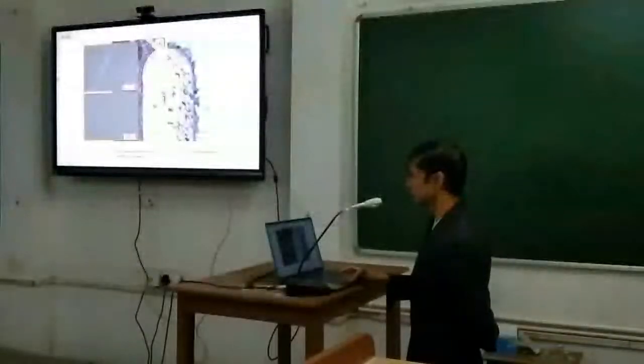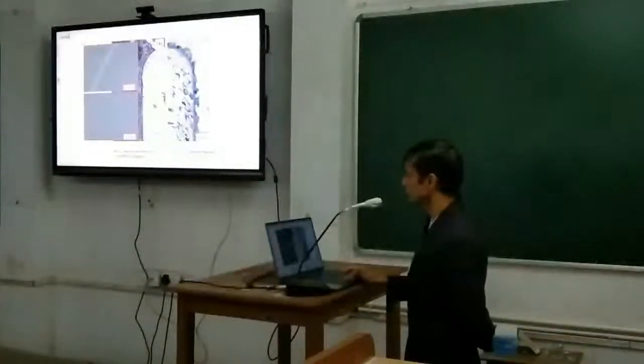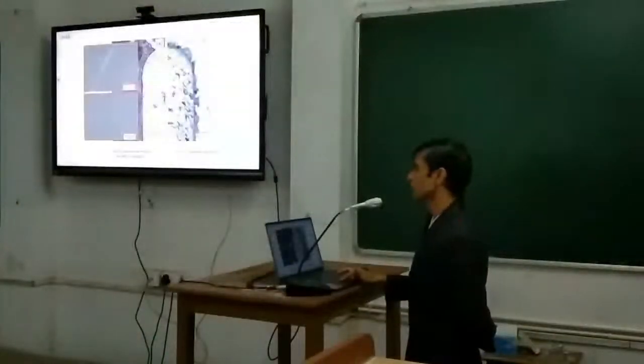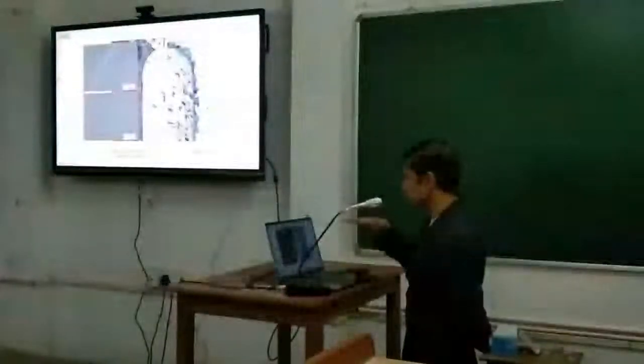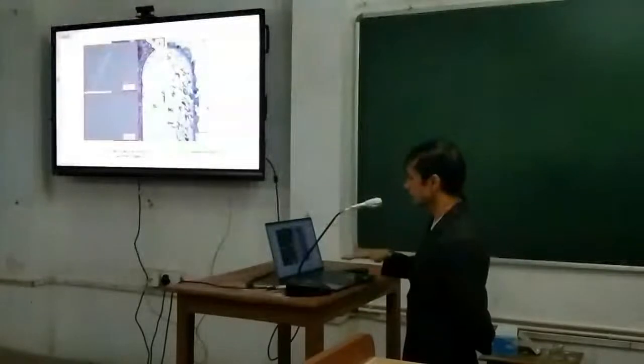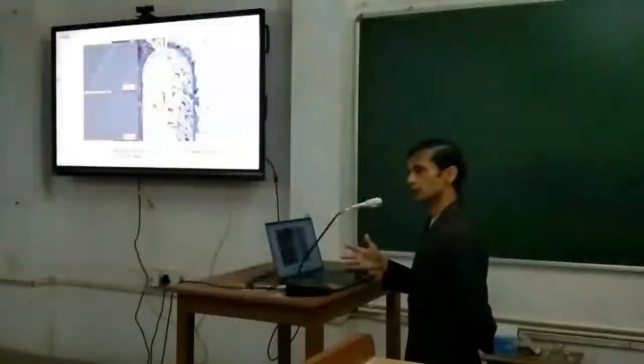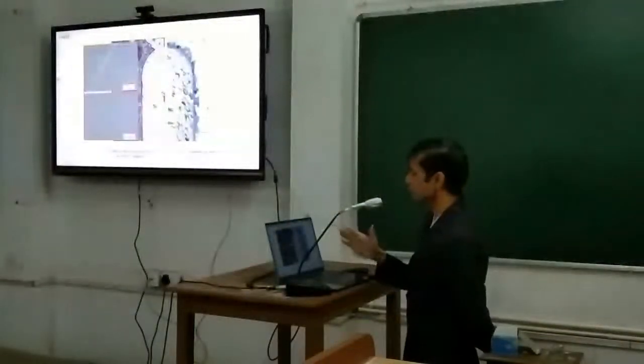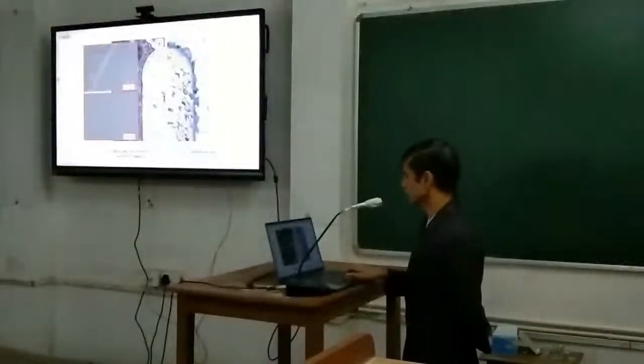On this side there is no sacrificial layer. When the tool keeps on moving, the grinding operation was performed slowly. Then you can see the chipping could be arrested on the side where there was a sacrificial layer. So this is basically just to arrest either the chipping or the bulging of the material. This is important for ceramic to avoid the chipping. It is important to avoid the bulging for the ductile material. So this is how it is done.